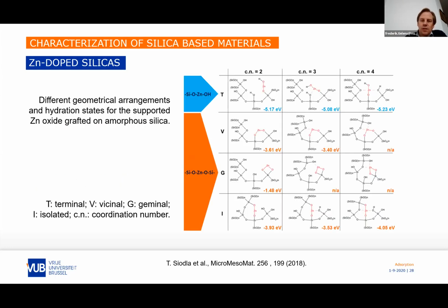So we did this also again systematically on different sites, different types of silanols, with different neighbors, and here we see that the interaction with the neighbors through hydrogen bonds is important for the stabilization. We have associated the energies here. This is also directly linked with the temperature and the degree of hydration. We can have a phase diagram, so we can clearly see at which temperature one species transforms into the other.